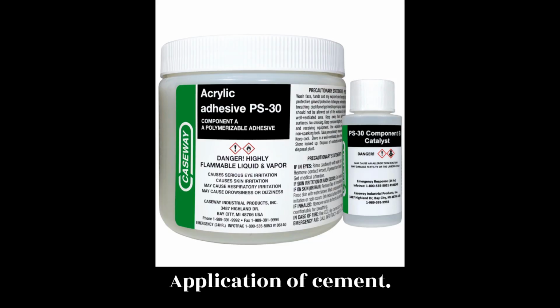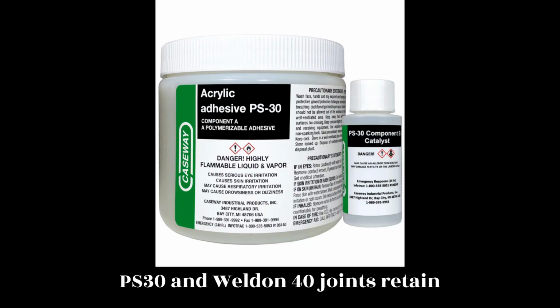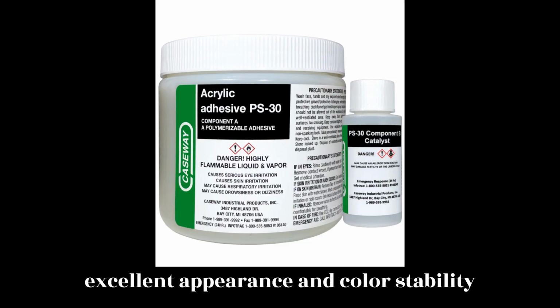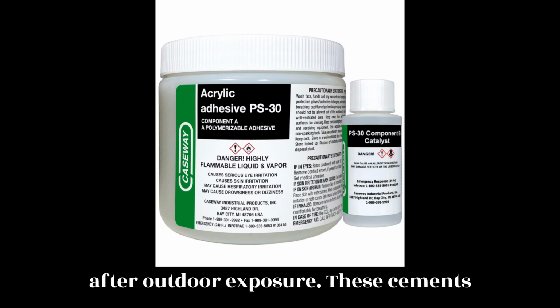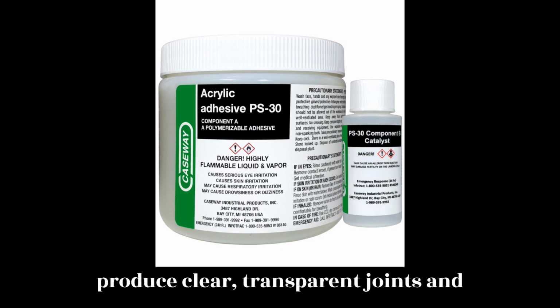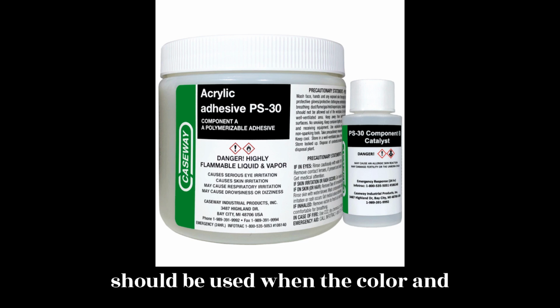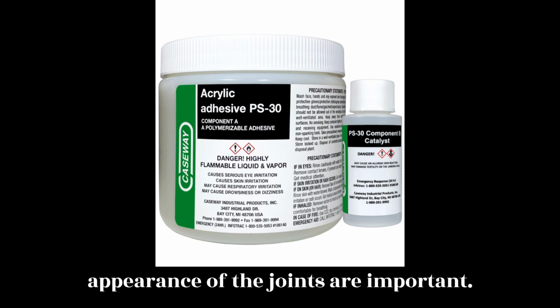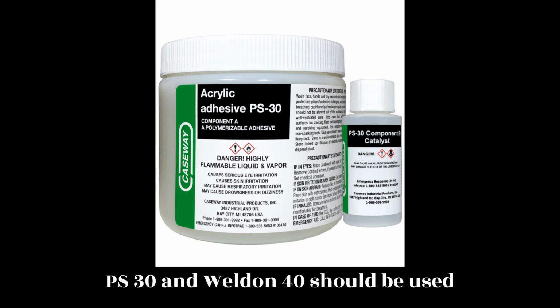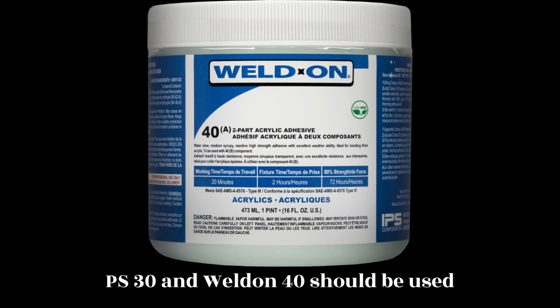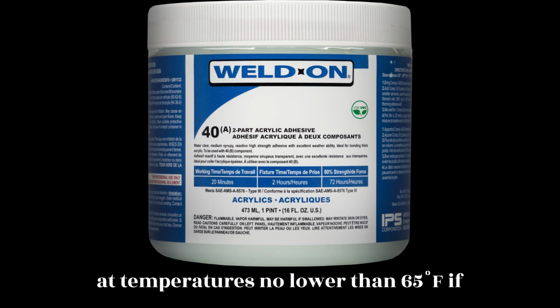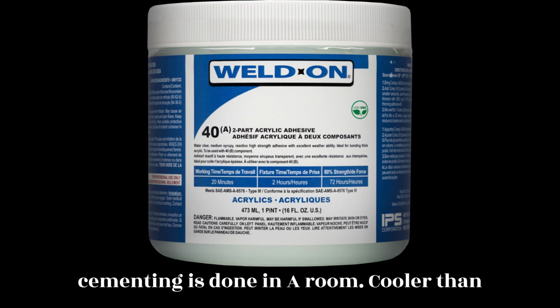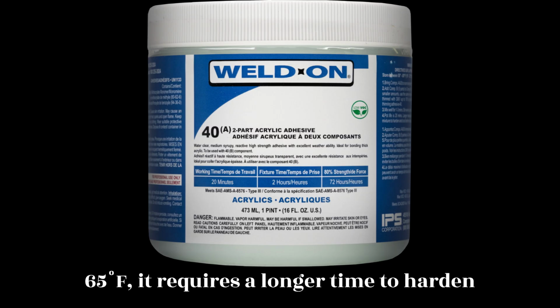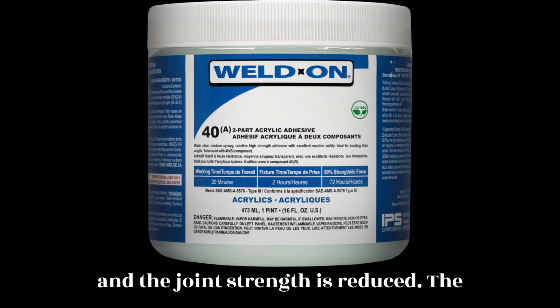Application of cement. PS30 and Weldon 40 joints retain excellent appearance and color stability after outdoor exposure. These cements produce clear, transparent joints and should be used when the color and appearance of the joints are important. PS30 and Weldon 40 should be used at temperatures no lower than 65 degrees Fahrenheit. If cementing is done in a room cooler than 65 degrees Fahrenheit, it requires a longer time to harden and the joint strength is reduced.